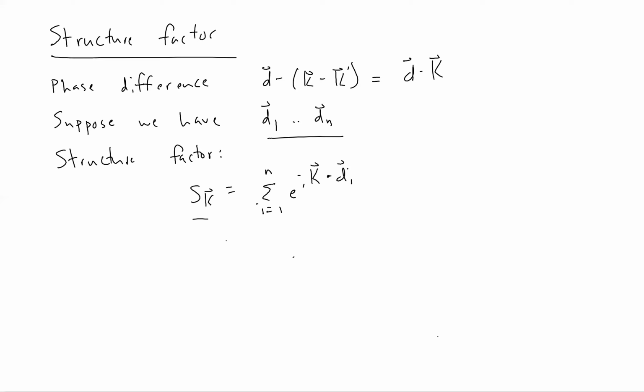The X-ray intensity associated with constructive interference at this reciprocal vector big K will go like S of K squared. So this is an extra intensity modulation that depends on the reciprocal lattice vector big K, which conveys some information about what happens at each lattice point. If it's not just a single scatterer, but there are multiple scatterers at each lattice point, you can look at the pattern of intensities as it varies between peaks to learn something about this.